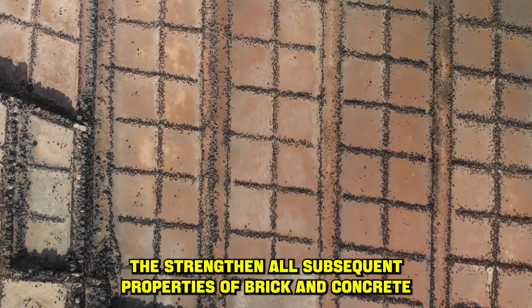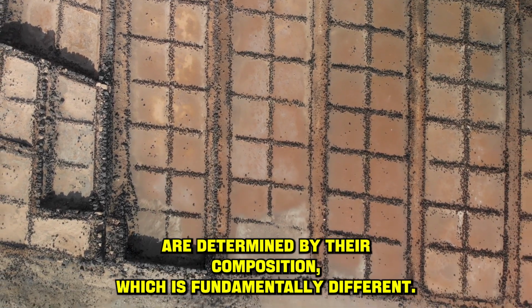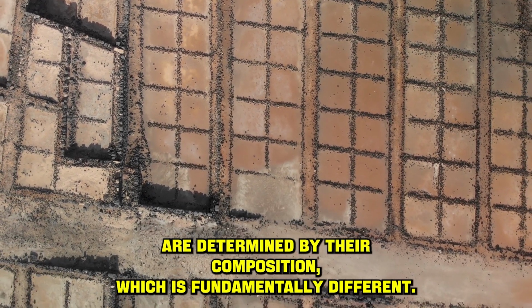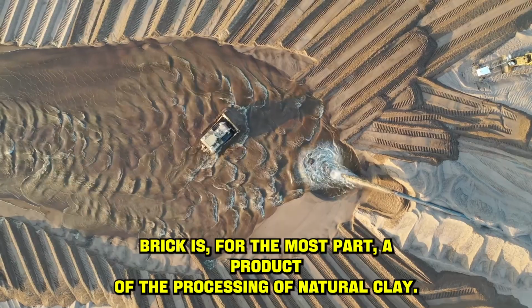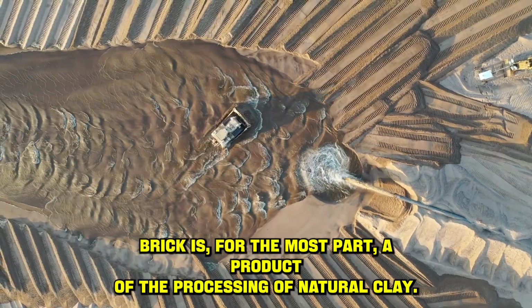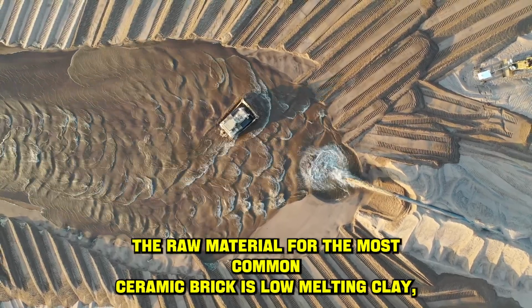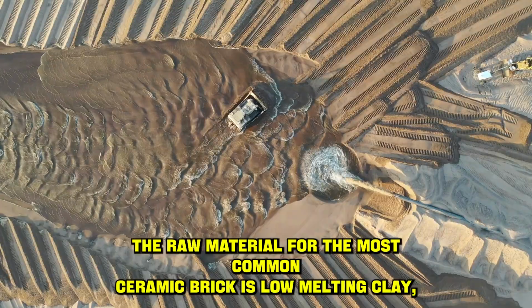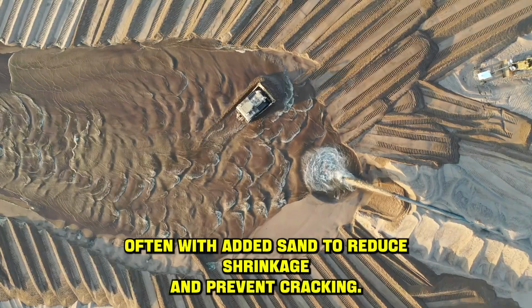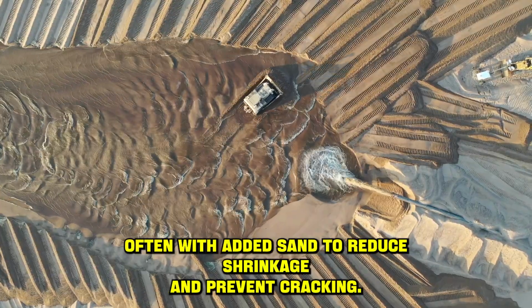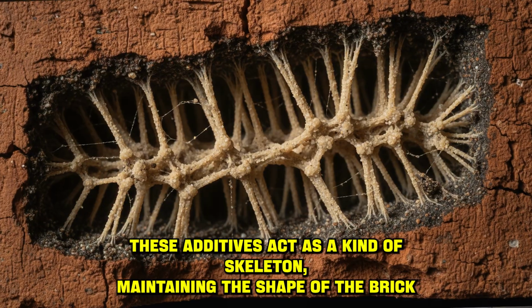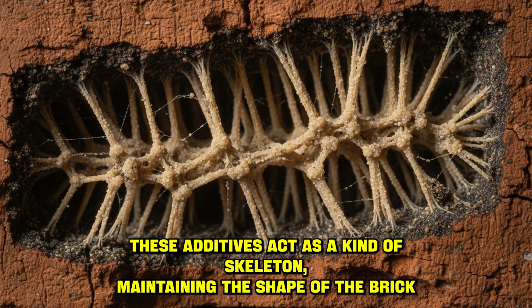our civilization. The strength and all subsequent properties of brick and concrete are determined by their composition, which is fundamentally different. Brick is, for the most part, a product of the processing of natural clay. The raw material for the most common ceramic brick is low-melting clay, often with added sand to reduce shrinkage and prevent cracking. These additives act as a kind of skeleton, maintaining the shape of the brick during drying and firing.